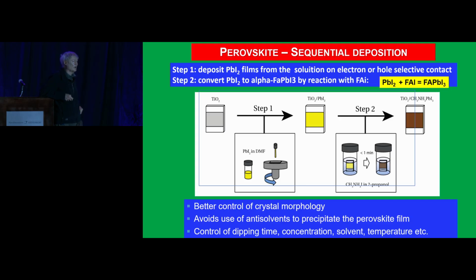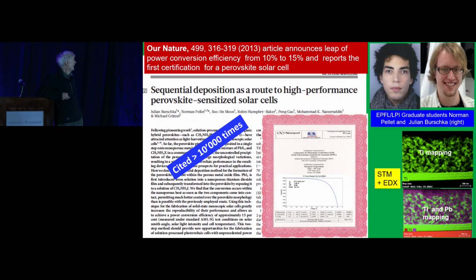What is that? Well, you would first put the lead iodide on your conductive support, be it hole selective or electron selective. And then you would have to convert it by reaction. The reaction is written up there with formamidinium iodide. So that conversion reaction works. It's described in a paper which we published about 10 years ago. And so there we used the titanium oxide, this nanocrystalline film, the same we had used for the dye-sensitized cells.